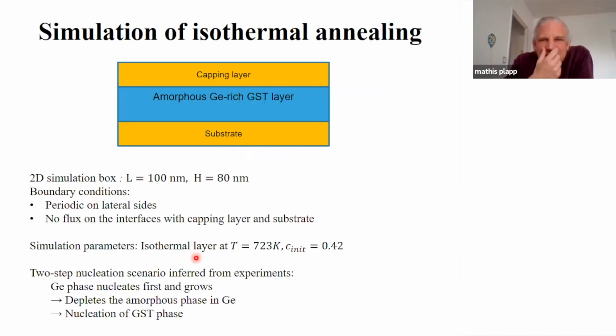And now we have done two types of simulations, and I will be finished in just 4 to 5 minutes. The first is the annealing of an amorphous film. So this is the considered configuration. We have a thin layer of the as deposited film, and then this is heated up until crystallization sets in. And from experimental observations, we know that the germanium phase nucleates first. So this we will use as initial condition.